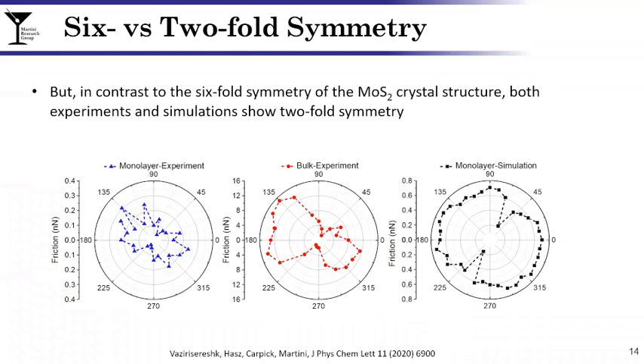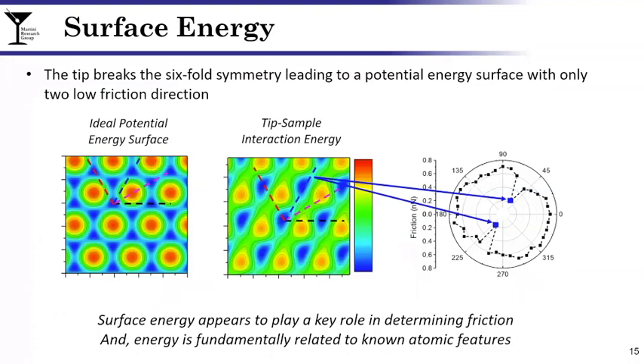This was quite confusing to us because, again, we're trying to connect friction to atomic structure, and we see some seeming discrepancy here. To understand this, we looked at potential energy surfaces. These colorful schematics on the left are the potential energy of the MoS2 surface. The one on the left is the ideal structure, where the red is high energy corresponding to the positions of the sulfur atoms in the topmost layer. And you can see that there should indeed be 6 ways you can go from the center line and get low friction.